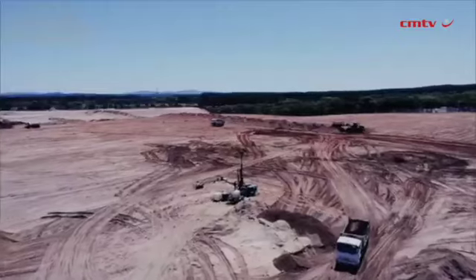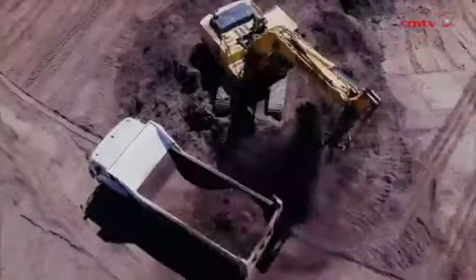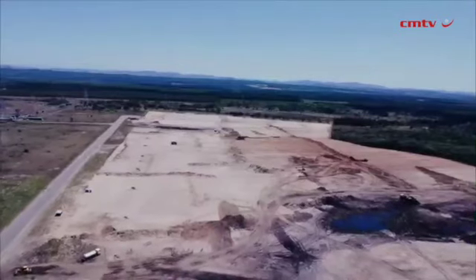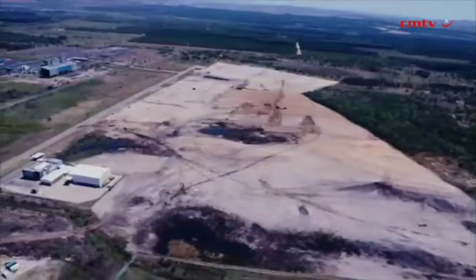And where will you get your ilmenite? Are you sure of getting it? So we use what we call sulfate ilmenite. Ilmenites are not monolithic, so you've got different types depending on the quality or the amount of titanium dioxide pigment. And secondly, what's also critical is the chrome content in some of these ilmenites. You'll find on our KZN coastal bed, the ilmenites have a slightly higher chrome percentage, making it not lucrative for our kind of process, because then the chrome has to be leached out, or you have to put in some processes to either roast it out or to take it out.